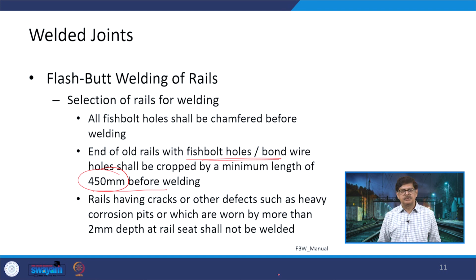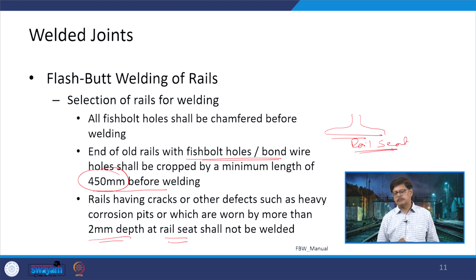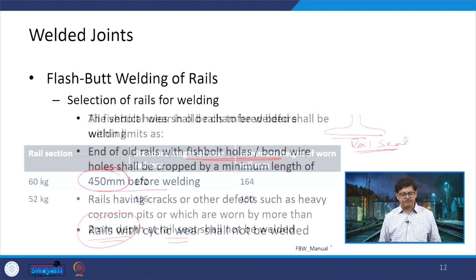The rails having cracks or other defects such as heavy corrosion pits or which are worn by more than 2 mm depth at the rail seat shall not be welded. So, there also we talked about if there is excessive wear or there is a corrosion, then that rail should not be used for the welding. Here also we are talking about the same thing, and here it also talks about the wear at the rail seat, that means at the bottom here which we are looking at. So, this is a rail seat location. So, if at this particular point the wear is more than 2 mm depth, then it should not be used.